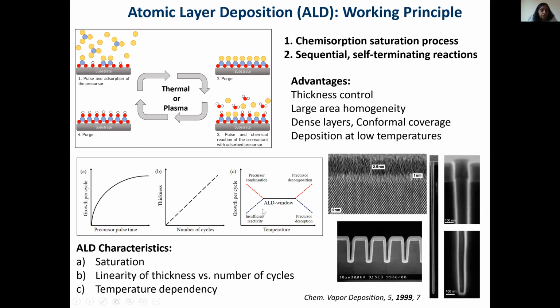So first you have to optimize the process, look at the temperature range where you get a saturated growth, and also where you can linearly control the thickness. And this is what we work on, especially the ALD window. So these are the typical characteristics that are very relevant. And you see here, if you see a trench, for example, how nicely one can coat the film on a trench substrate, or you can also see the nice, very clearly demarcated interface between the film and the substrate. So we are talking about nanometer thick layers, a couple of nanometers, 1, 2, 5, or not more than 50, 100 nanometers. Then you go to the CVD range, okay?